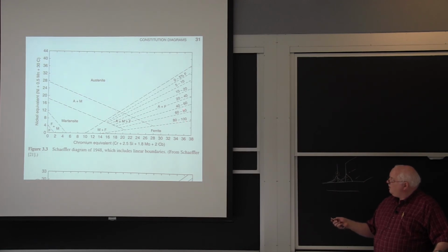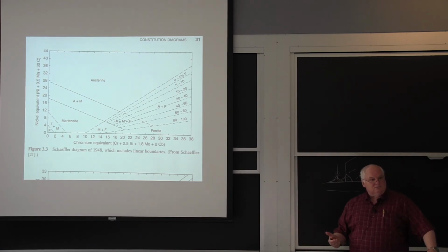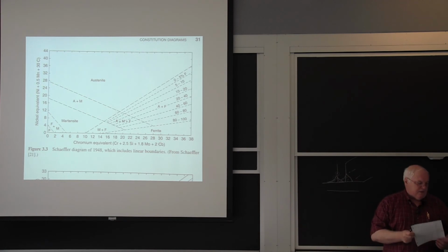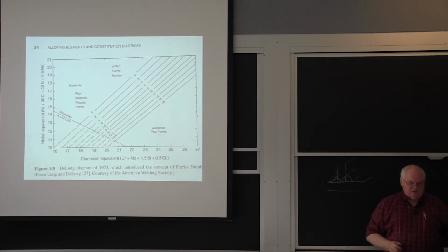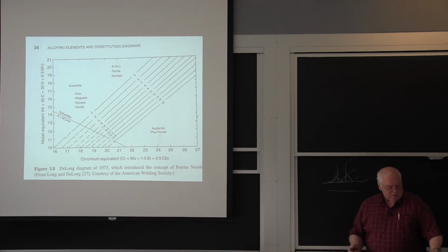So this is 100% ferrite, go all the way up here to 0 to 5%. And we found it's nice to have your weld metal right in here if you're welding something down here. So we use 308 filler metal, which is slightly adjusted in its composition, so it'll give you like 3% ferrite in the weld metal, and you wouldn't get cracking because of the sulfur in these highly restrained weldments.